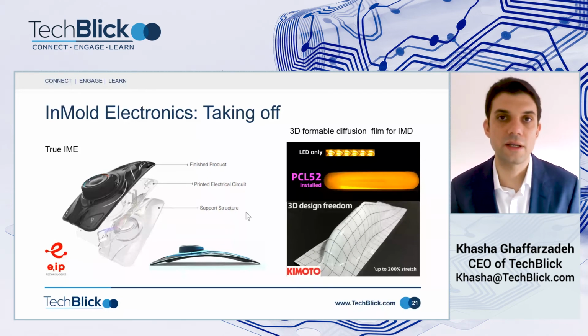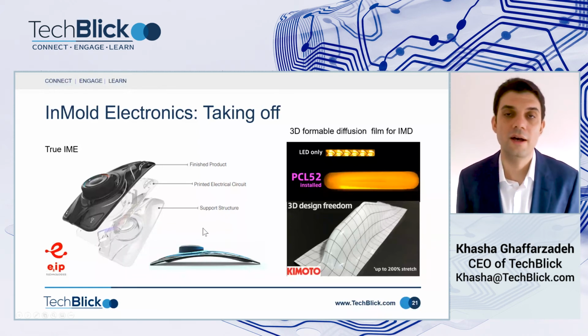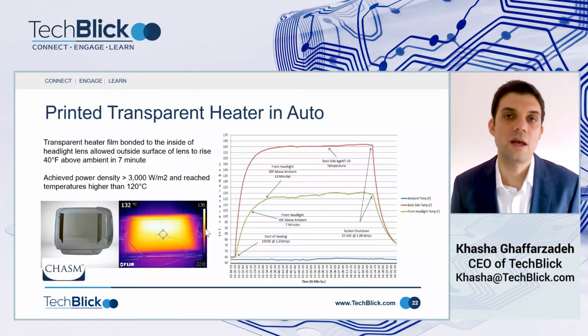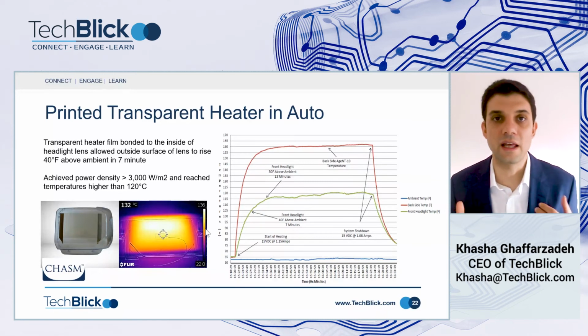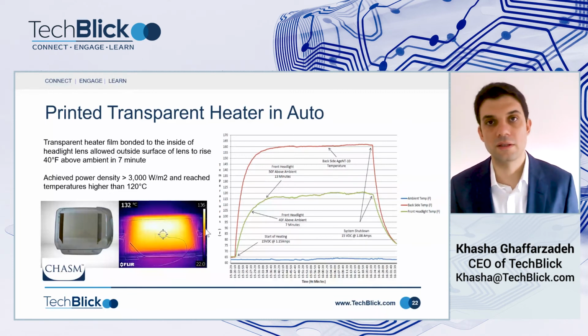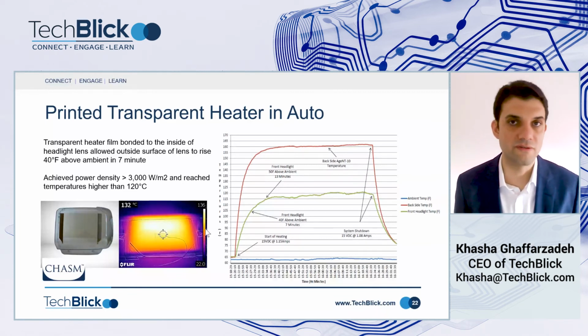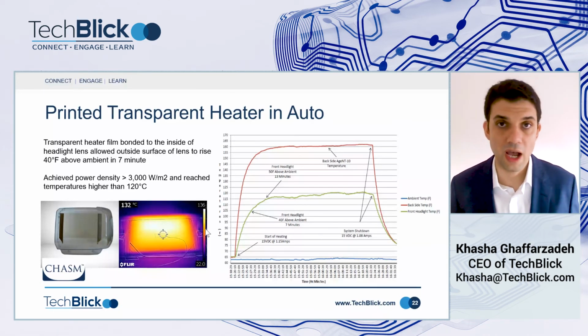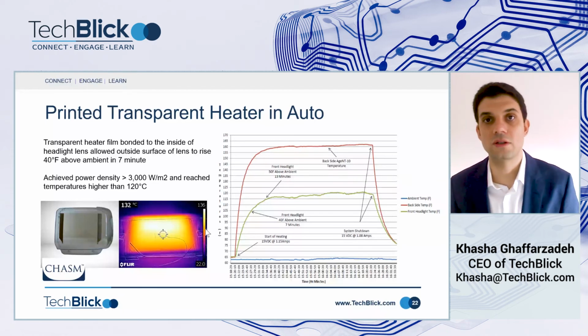Printed transparent heaters, excuse the pun, but really a hot area, because there are not so many good solutions out there for printing transparent heaters. And a lot of the solutions that are emerging involve printing. So one approach is to embed very, very fine trenches inside of the substrate, place your seed layer and then electroplate, so that you end up with very fine but deep embedded copper lines, highly conductive, in your substrate, and achieve very, very good results over large areas with very fine metal mesh features. So having both very low resistivity and very high transparency.